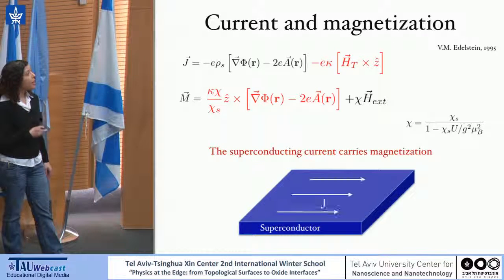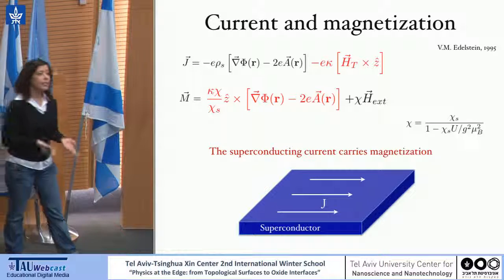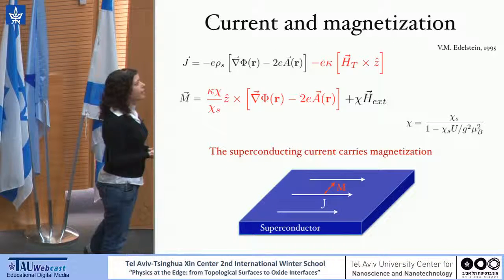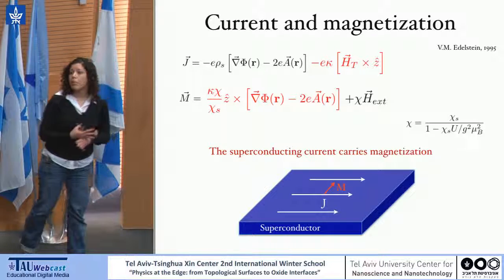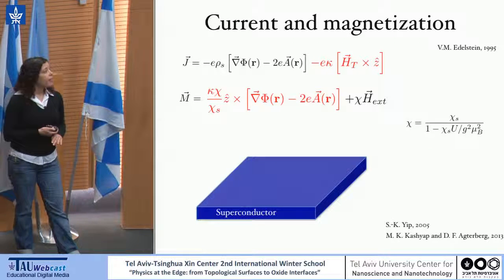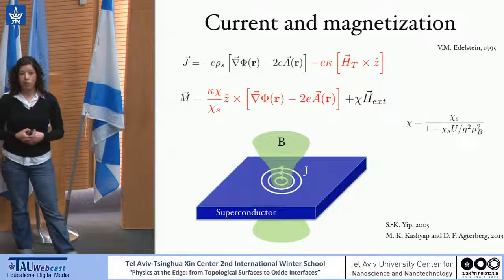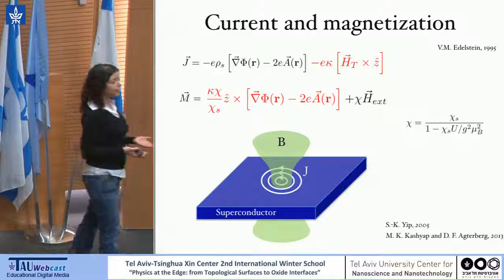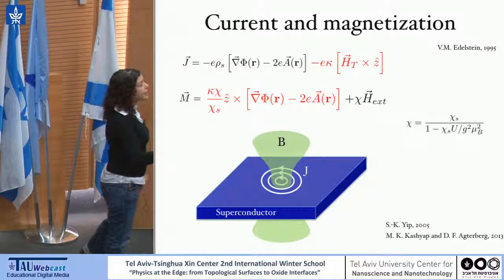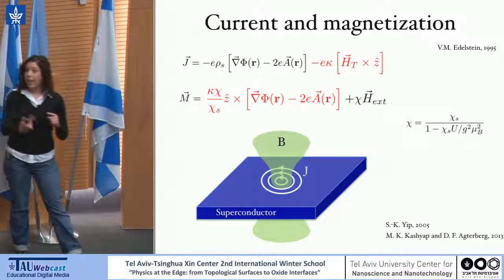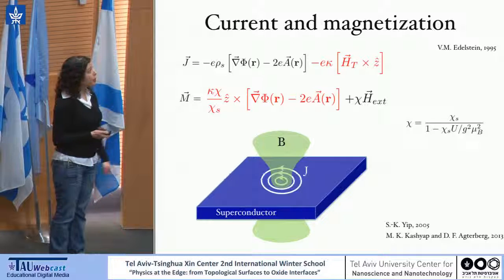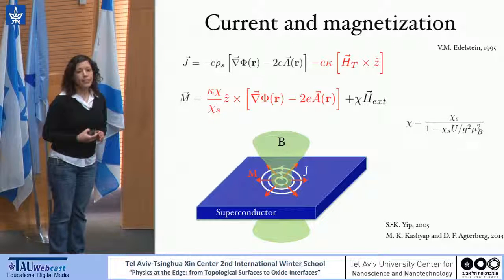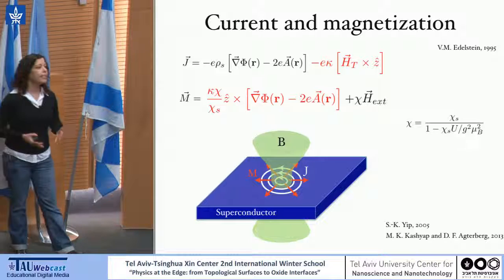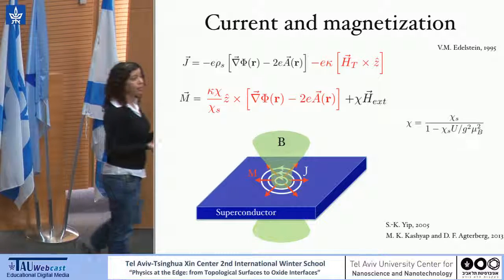Which means that if we look at currents inside the superconductor, they are actually carrying magnetization perpendicular to them. If we consider a vortex in such a system, so we have current circulating around some area of the superconductor, it will have a magnetization structure that actually resembles a magnetic monopole.